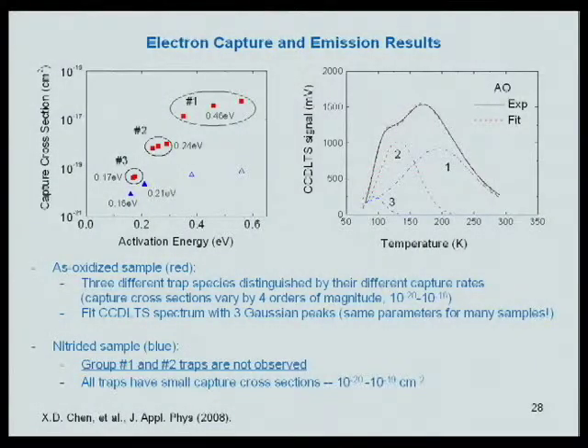Now, further, what we find, the blue points represent the measurements in the nitrided sample, and what we find is that all of the traps in the nitrided sample have very small values of this capture cross-section, and that's telling us that these group 1 and group 2 traps have been changed by the nitridation process. In other words, those energy states are no longer there. They're somewhere else, but we don't detect them anymore.